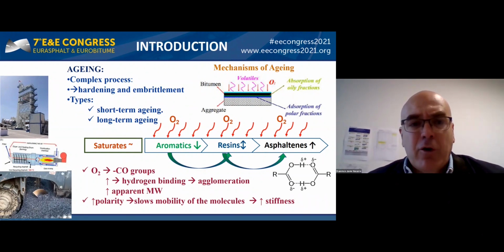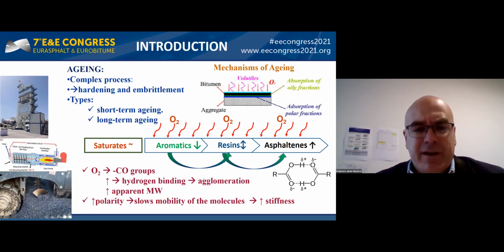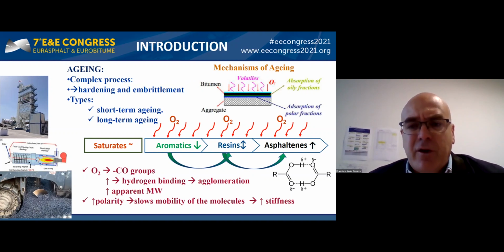The most intense one, called short-term aging, takes place at high temperatures during processing operations such as mixing, storage, transportation, laydown, and compaction. Secondly, the so-called long-term aging happens slowly during years at ambient temperature and results from the environmental conditions while in service. In general, aging is a very complex process which involves different mechanisms such as oxidation, volatilization, exudation, etc.